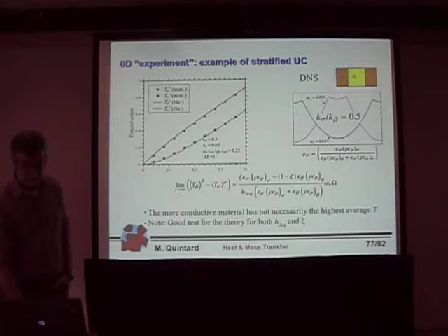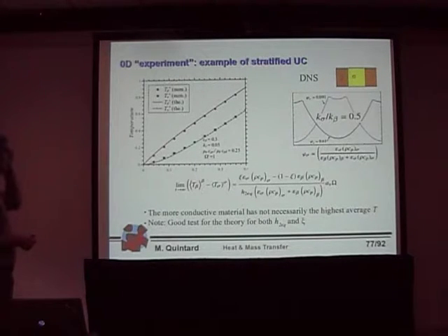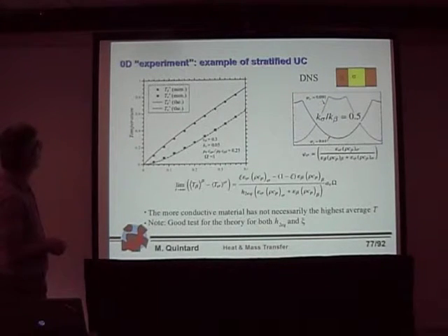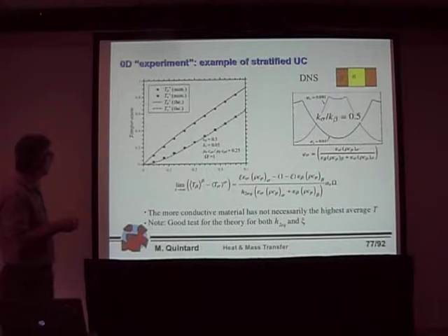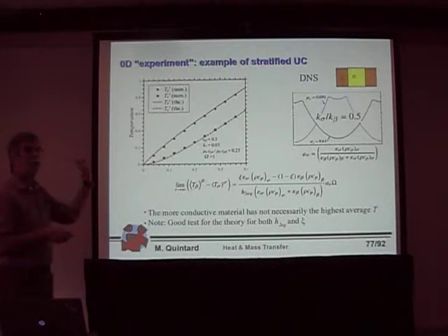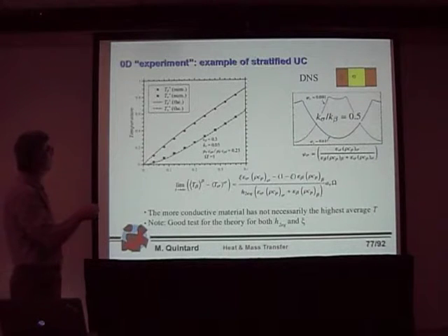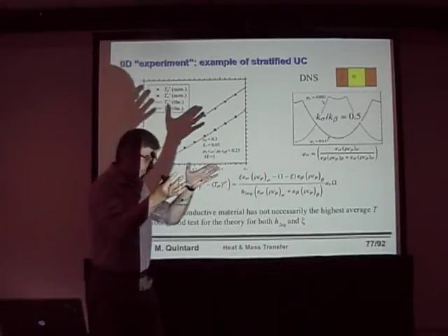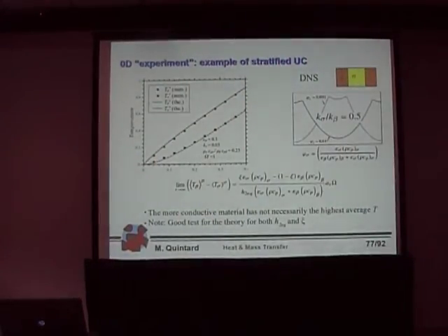And let us take an example of application. I have a stagnant system, and then homogeneous temperature, and then I introduce some heat at the interface, and basically I will have the following situation. The temperature of both phases at the macro scale will increase. There will be a transient evolution. Everything is transient, but if I look at the difference between the two macroscale temperatures, then after a while, the two temperatures increase, but the difference remains a constant. And this difference can be predicted by the two equation model with this distribution coefficient.